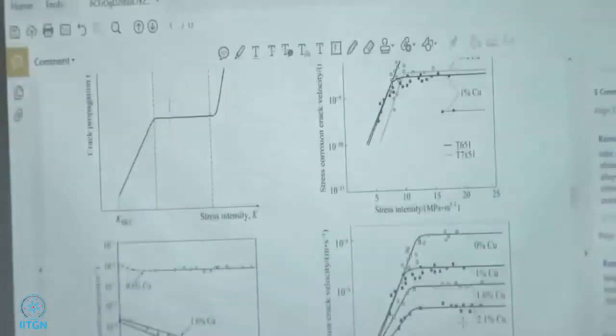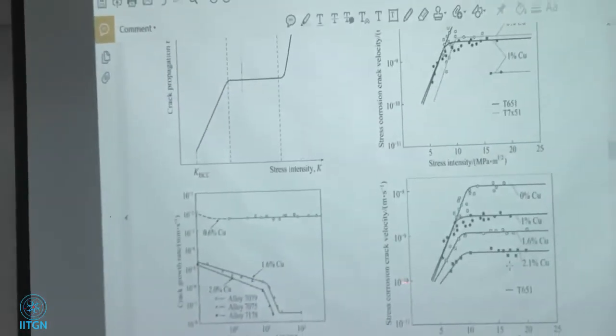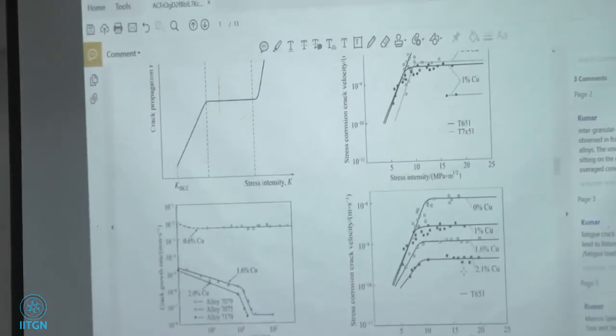KISCC is like a threshold, right? The stress corrosion cracking threshold. That means below this stress intensity, there is no crack growth. But there is a lot of change, maybe 1.5 to 2 orders of magnitude, in the crack velocity.